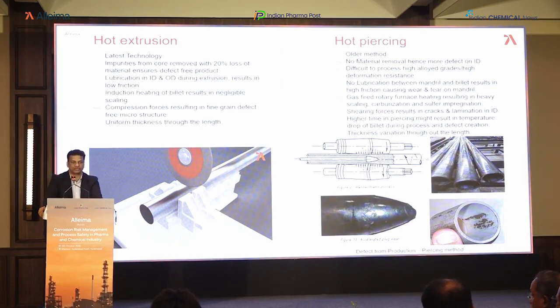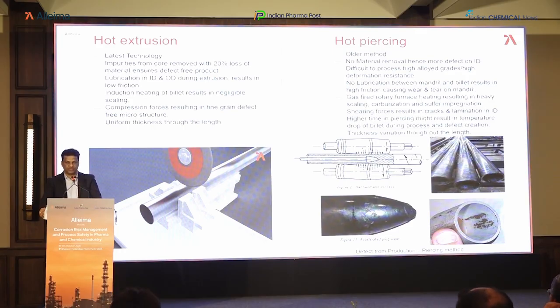Hot piercing is an old method, and hot extrusion is a newer version of it, which improves the quality. So this is the latest technology. In any material, the last portion to solidify is the center, and all the impurities get segregated at the center, so we need to remove that impurity. During the hot extrusion process, we remove the core of the bar. It helps to remove the impurities. Also, it helps with ease of hot extrusion. So the major operation is to remove the impurities from the center of the tube. Also, it has a compression force in it, and you get a uniform thickness all across the tube.